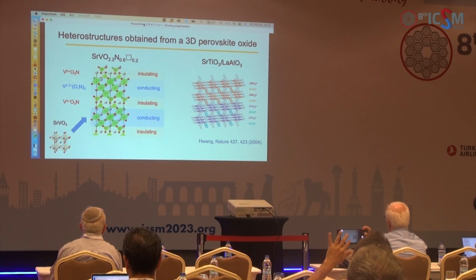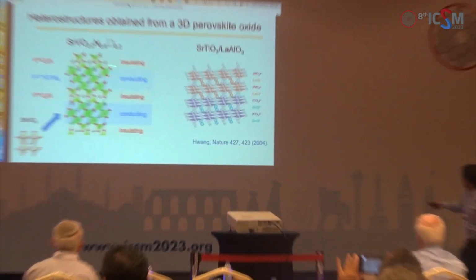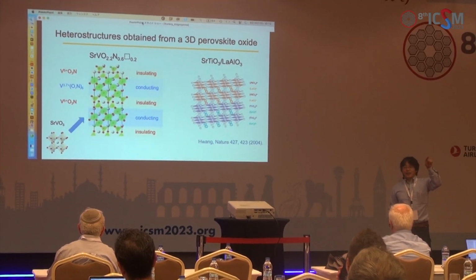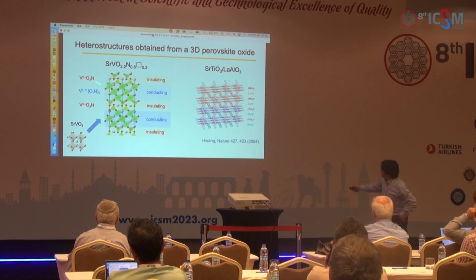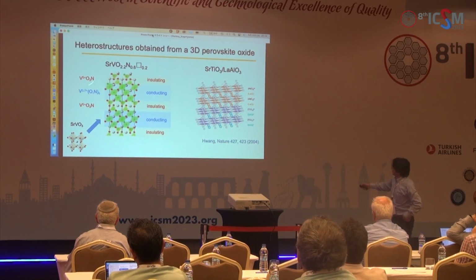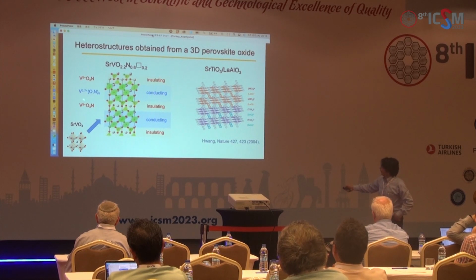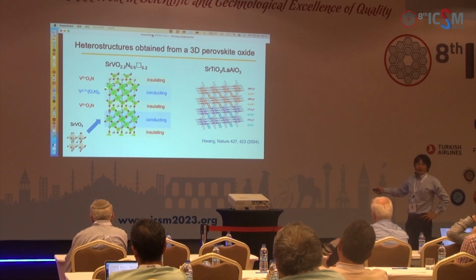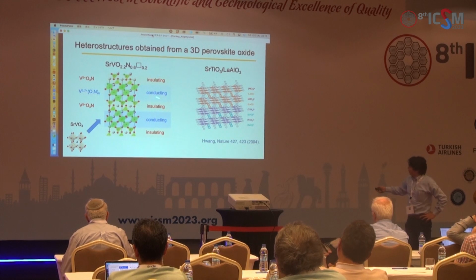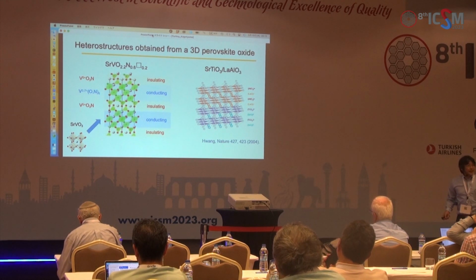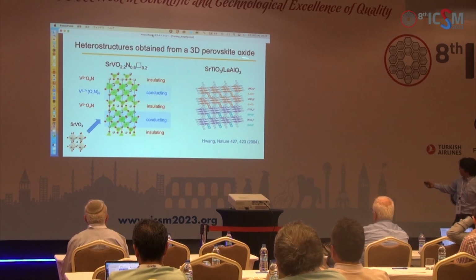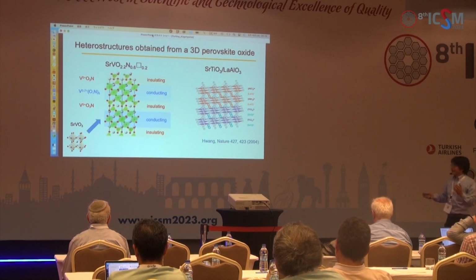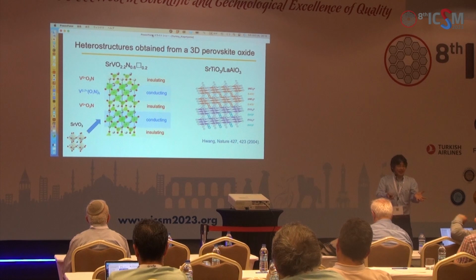What is happening here is very interesting. In this tetrahedral layer, as I mentioned, vanadium 5+ doesn't have electrons, so this is an electronically insulating block. While in this octahedral block, you have a vanadium valence of 3.7, so you have a conducting state. This reminds you of the artificial thin blocks made by using different types of units. This is very famous work by the Stanford group. But now we started from this simple three-dimensional structure, and a similar thing can be done with these topochemical anion-exchange reactions.